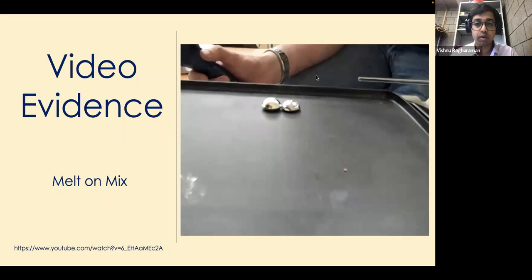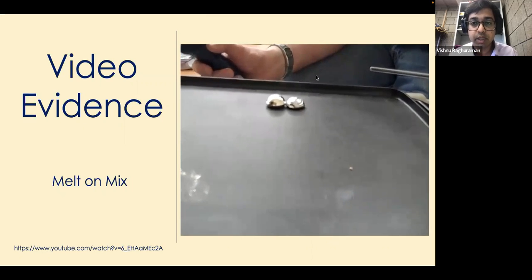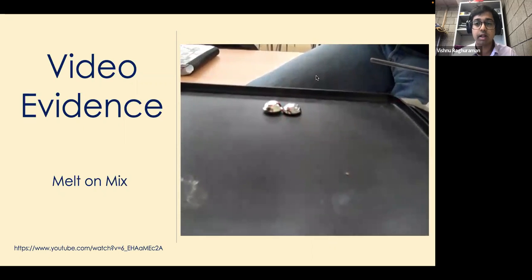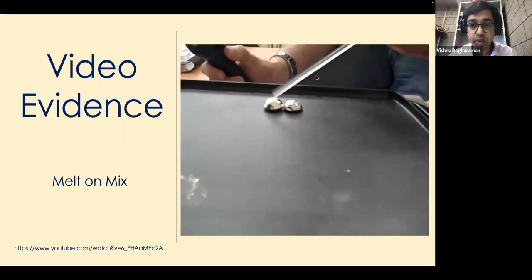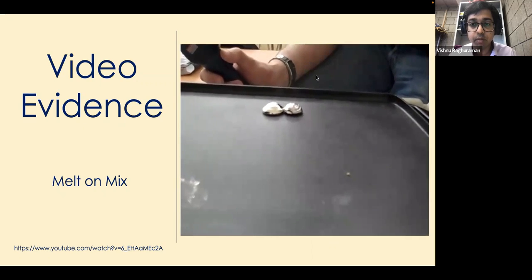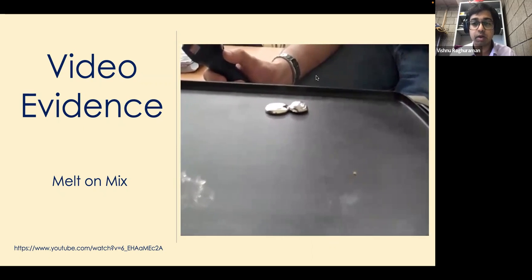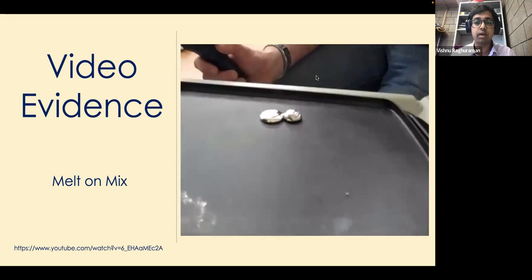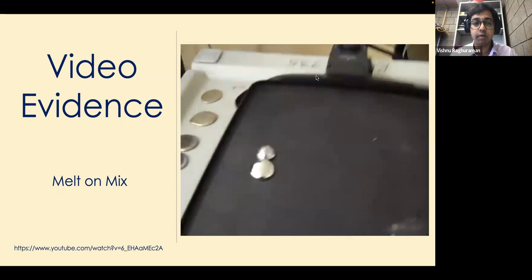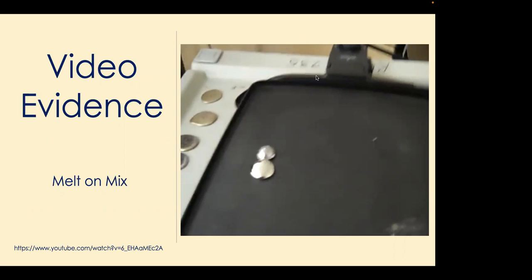And we can see that here. So I have a video here. Basically, there's hot tin and lead, and they have been put in contact together. And then you can see that without adding any additional heat, it has melted because an alloy has been formed, and that particular alloy has a lower melting temperature than the individual components. So this is, in fact, the principle on which solder is based. So solder is solid and it has a low melting temperature when you add these two together. And then you can use that to create liquid, and then it solidifies quite easily.